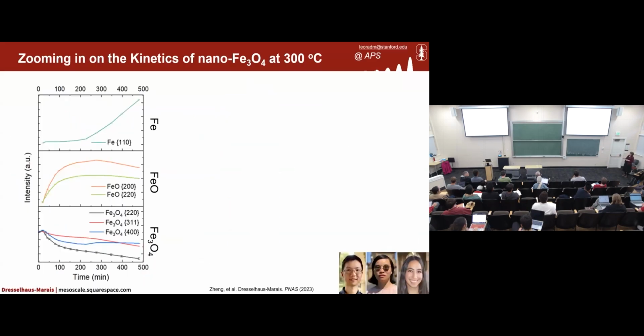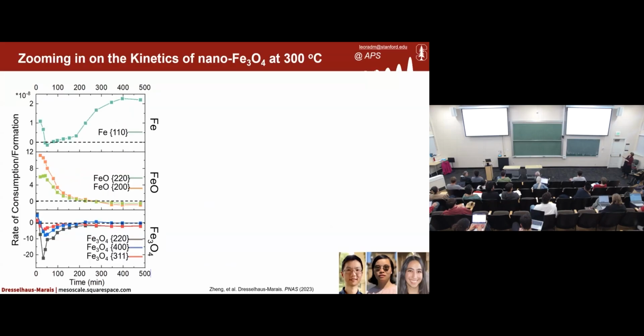So we dug in a little deeper and tried to understand what exactly is going on. And what we found is that although we like to describe this as just a simple system, one phase to the next phase, the phase actually is not the same in every direction. And so ultimately what we found is that as you resolve the directions that are relevant to this material, you see that the rate of consumption of each species is different along the different crystallographic axes.